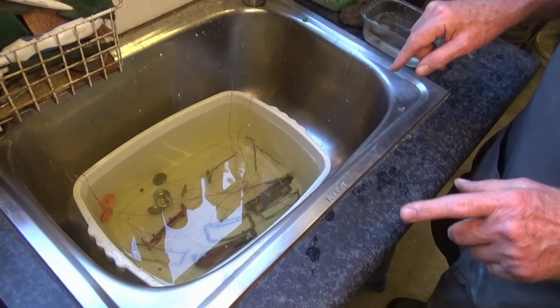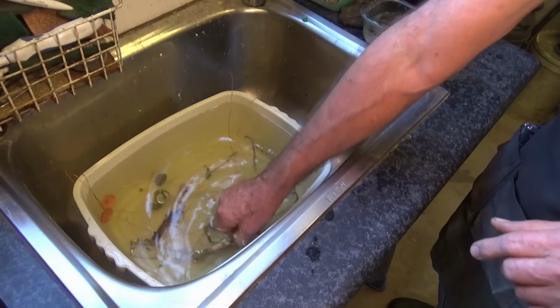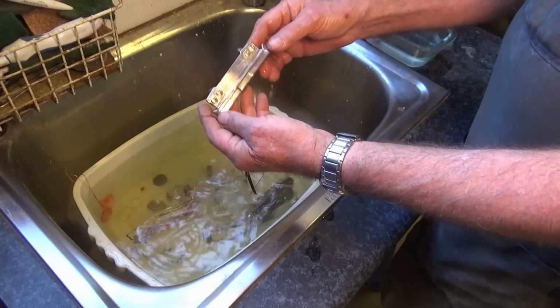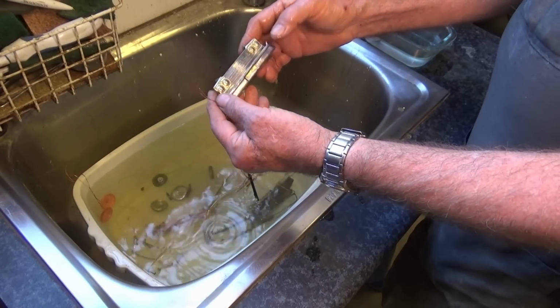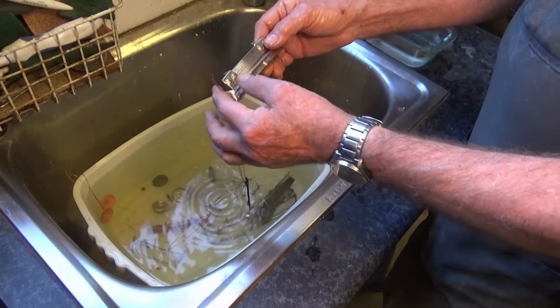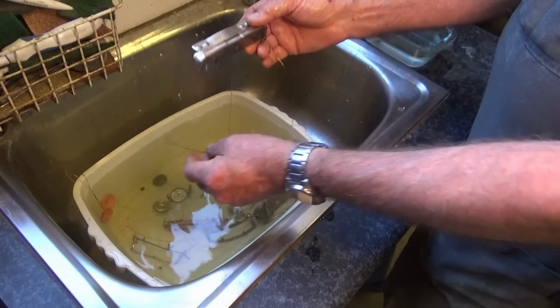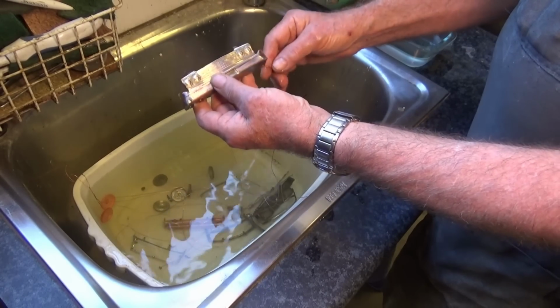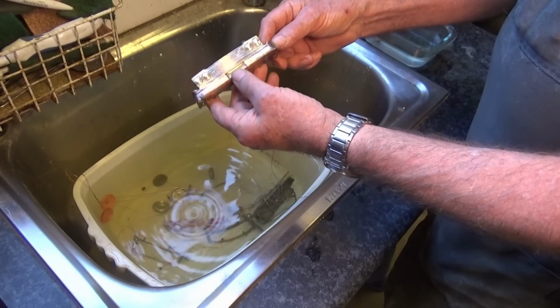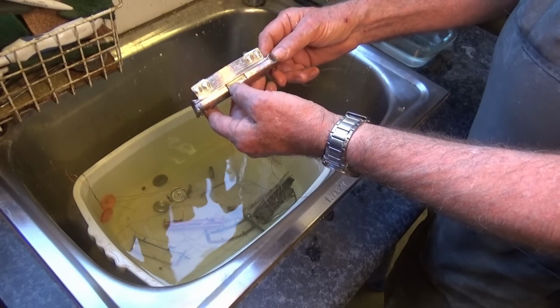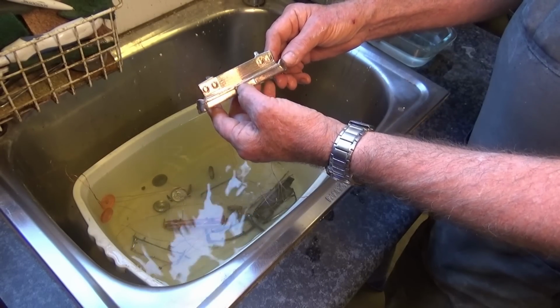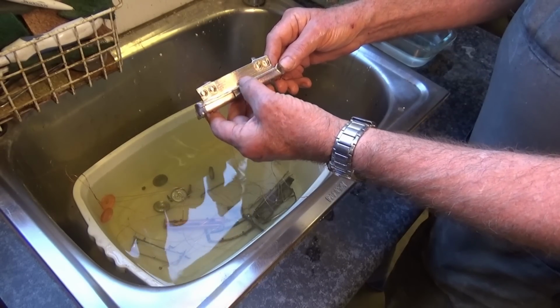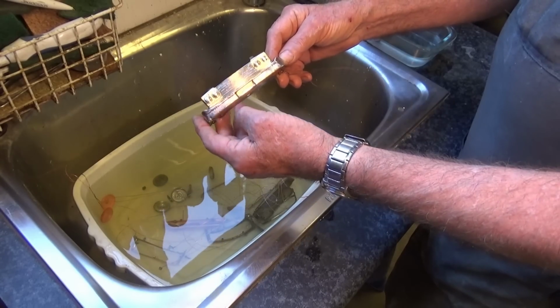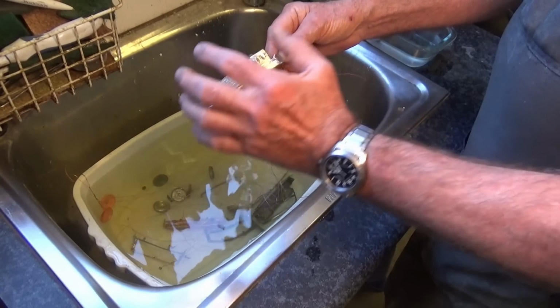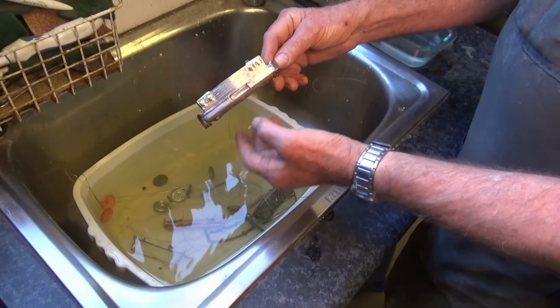Now, what I've noticed is that some of these parts still have chrome on them. I just can't get it off easily, and where the chrome is visible, the copper plate doesn't like to deposit over that existing chrome. But what I'm trying to do here is to get the copper to go onto the bare steel. So when we do the nickel cobalt coating, it will give us a uniform finish on both metals, on the chrome and the bare steel or the copper that's over the top of that.